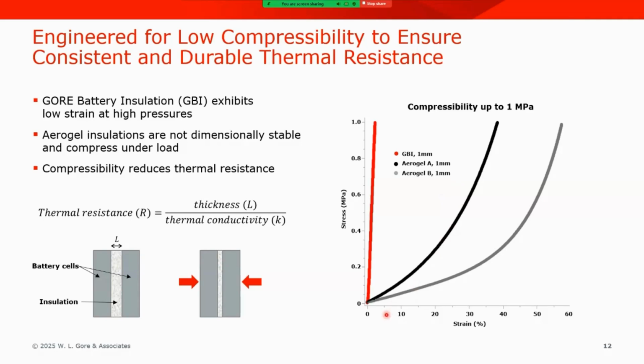So you notice as we begin to put compressive stress on the material, the aerogels, being compressible materials, show significant strain. In the case of Aerogel A, up to about 35% decrease in thickness. And with the more compressible Aerogel B, we're at about 55% decrease in thickness. So we're going to be starting with 1 millimeter and decreasing. Compare that to the GORE battery insulation, where we're starting at 1 millimeter, applying that same amount of stress, and you see that the compressive strain is less than 5%. So that means that the thickness value is not going to vary with compressive stress, and that in turn means that the thermal resistance is going to remain constant and durable during this entire condition.